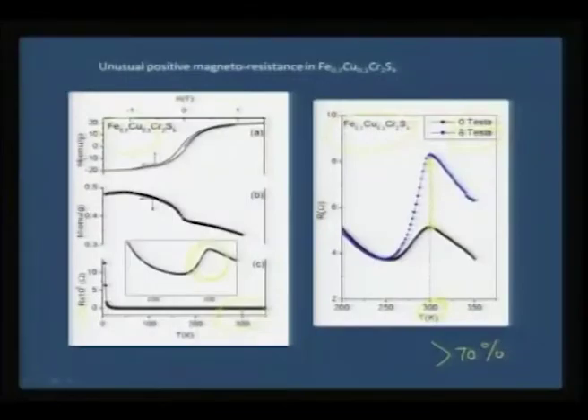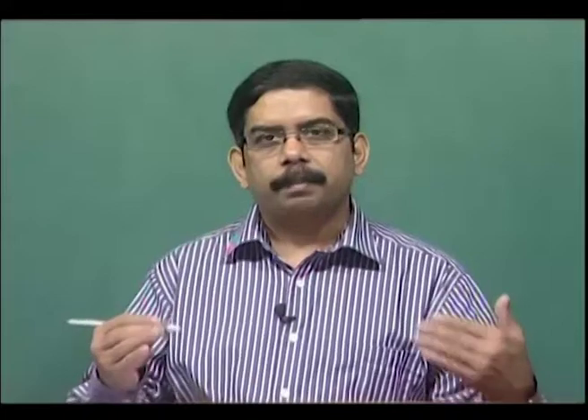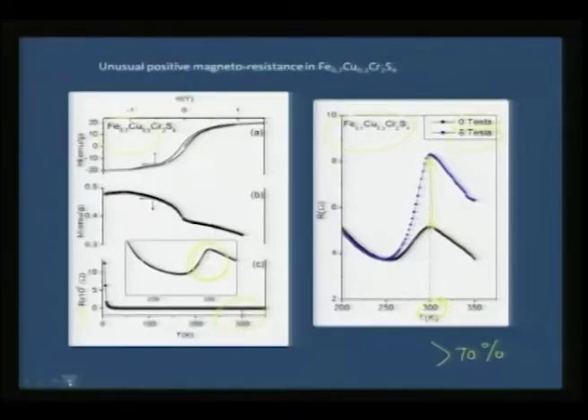Not only that, you see here that when you apply a magnetic field, the resistance is higher compared to the resistance at 0 Tesla, which means the magnetoresistance here is not negative, but positive. So, what is reported is a negative magnetoresistance, but what we see here is a positive magnetoresistance at room temperature. Therefore, this is also typical of the method that we adopted to prepare these sulphides. So, this is reported for the first time. It has appeared in Journal of Applied Physics in the year 2008.